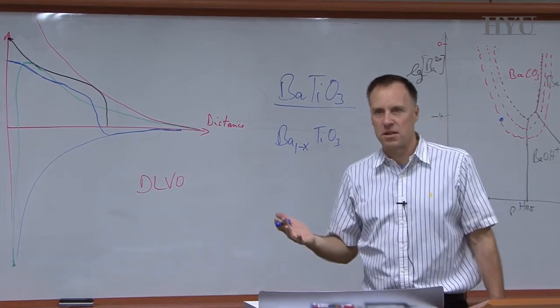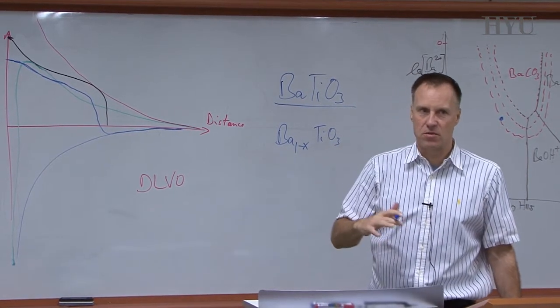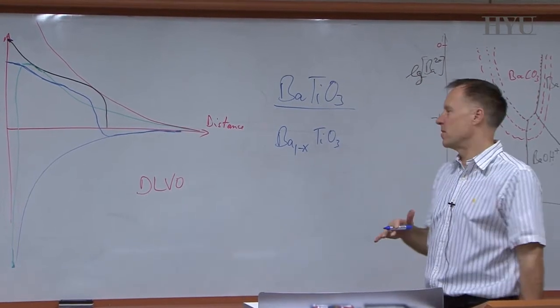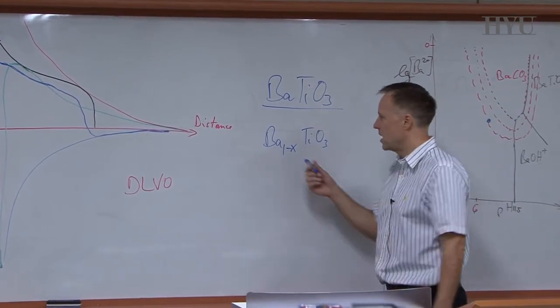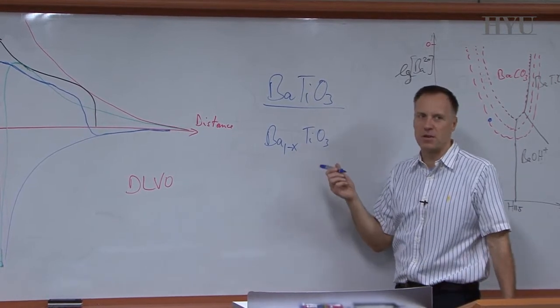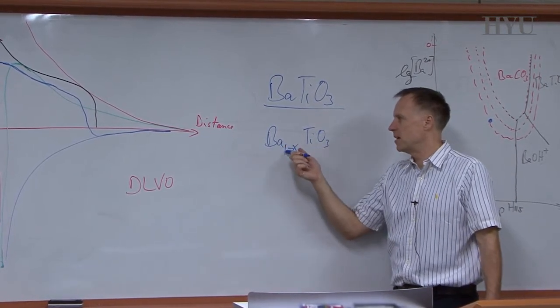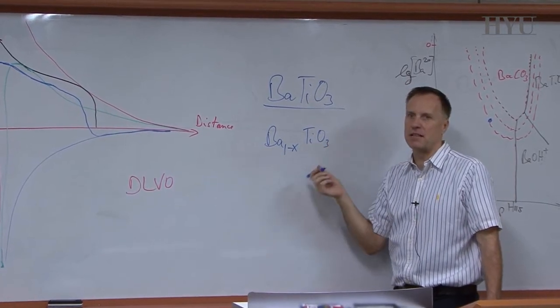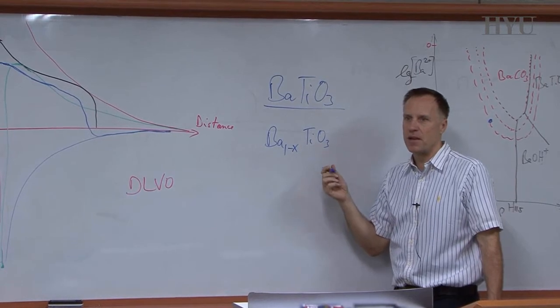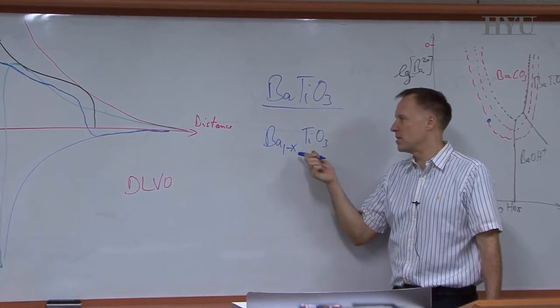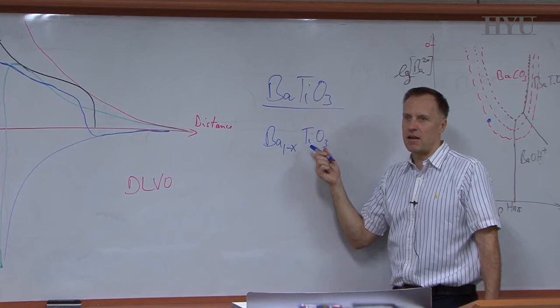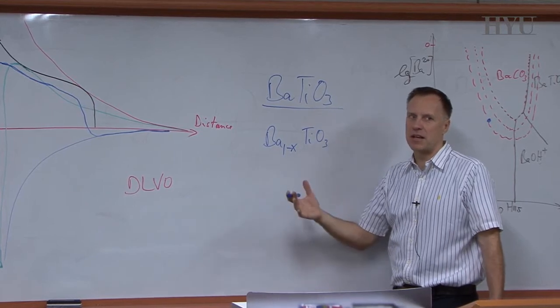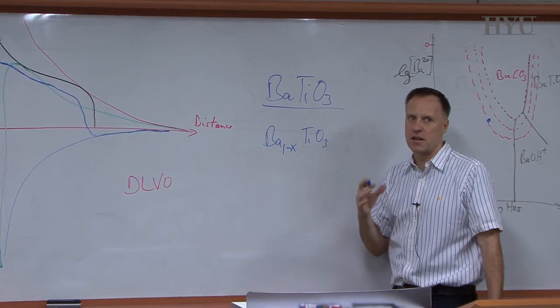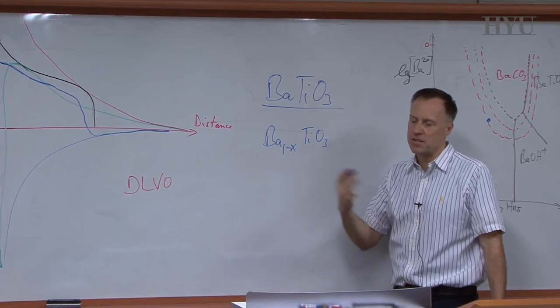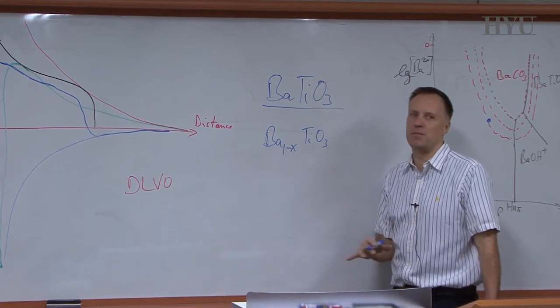you are not in a solid state sintering process, you're in a liquid phase sintering process. We can't go there right now. All these things you need, it's a short time frame to look into the phase diagrams and so on. But you change the phase diagram basically here by moving to a titania-rich system. And this has a liquid phase forming at lower temperature. And therefore, when this material sinters, it is controlled by liquid phase sintering, which means you can get exaggerated grain growth under the conditions that you usually sinter, because you don't expect it to be barium deficient.